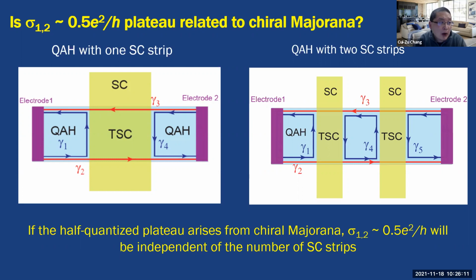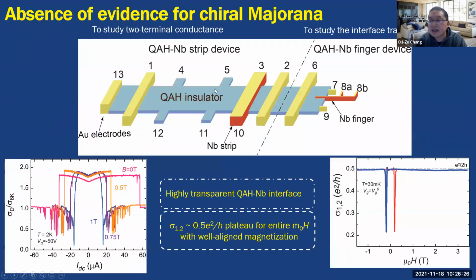And one thing I want to point out is that in our experiment, we only exclude the observation of the e²/2h plateau being related to chiral Majorana in millimeter-size devices, maybe 100 micrometers in this kind of device. We don't quite know when the device becomes very small. For example, in nanometer devices, in tens of nanometer devices, it may be possible to use this kind of geometry to demonstrate the Majorana physics in quantum anomalous Hall and superconductor hybrid structures.